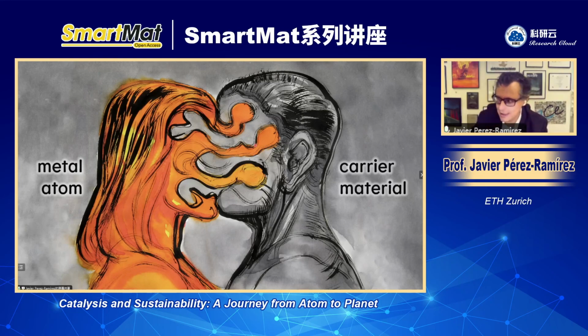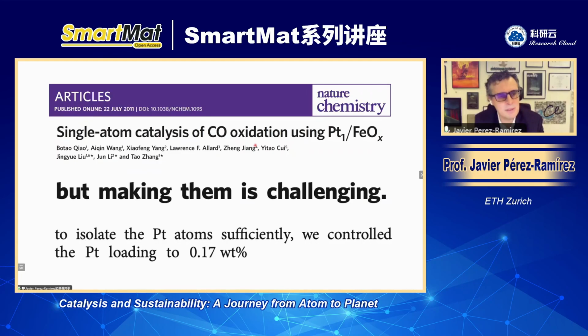Now, making single atom catalyst is not easy. And the first paper that was coining this term, single atom catalysis, published by Tao Zhang and Jun Li in Nature Chemistry back in 2011, said it very clearly, right? They say that making this single atom catalyst that they use for CO oxidation is very challenging. And in order to make them in isolated form, so that there is no clustering of the metals, they had to control the platinum loading to very low values, so that there would be no clustering, essentially 0.17 weight percent.